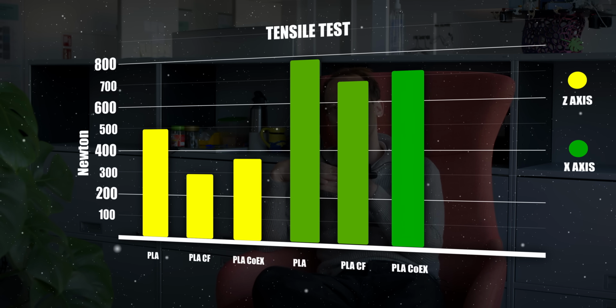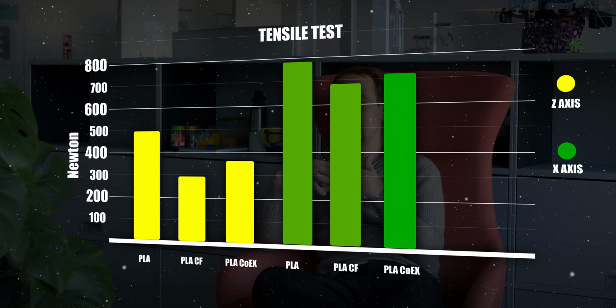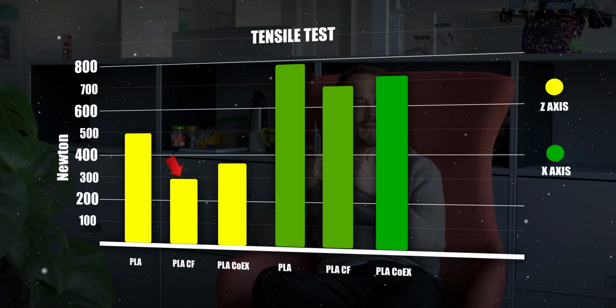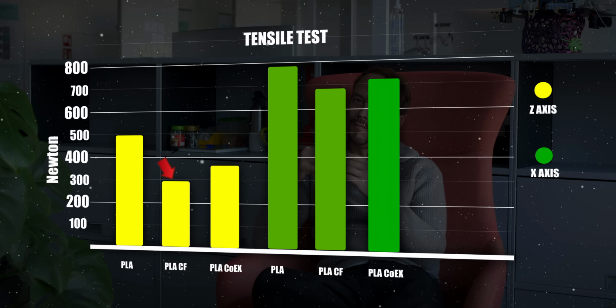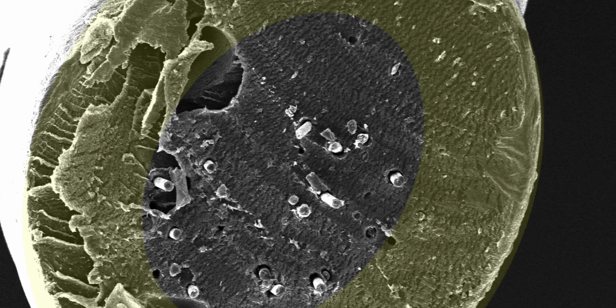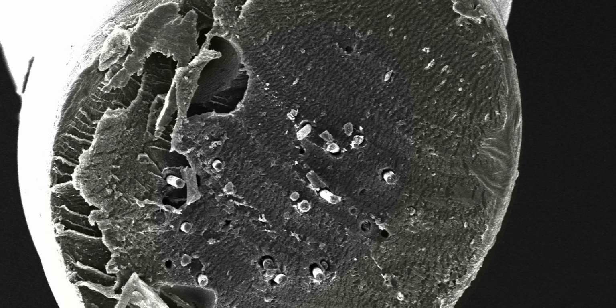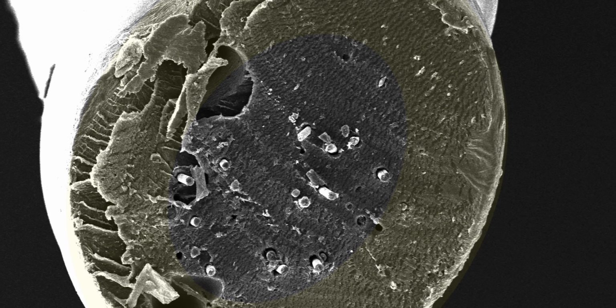especially the Z one is the interesting. And as you can see here, yes, it actually holds better, but that was kind of predictable because the layer bond is not disrupted by the carbon fiber anymore. I think for me the biggest surprise was actually that the carbon fiber stayed in the middle of the extrusion and didn't touch the layer boundaries. So that is what gives this material an advantage over carbon fiber reinforced PLA.